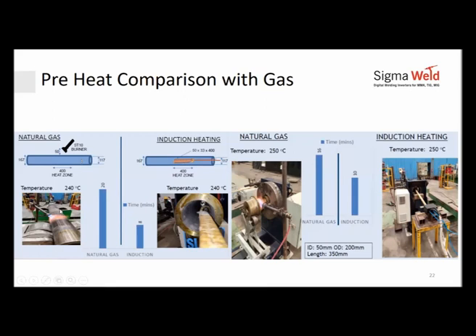This is the burner that was used. And the burner, while the job is rotating and the burner is at a fixed position, when they tried to heat the zone of 400 millimeters, they were able to achieve 240 degrees in 20 minutes. But again, if you can see, the burner hits at one place at a time, you will have bright hot spots in some places and not so hot, or not the equivalent temperature of 240 degrees all across the surface.